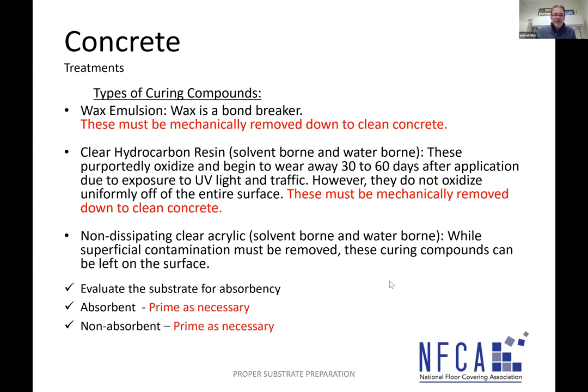And check with your manufacturer, but if you're 100% certain with what curing compound was used and it falls into this category, it's possible to prime and it's possible, whether it's absorbent or non-absorbent, to prime and install a patching and leveling material. But test areas should be done on site, because manufacturers are not out there testing their products over all different types of curing compounds or sealing compounds. If there's any type of doubt, mechanically remove it down to concrete and take all risk out of the equation.